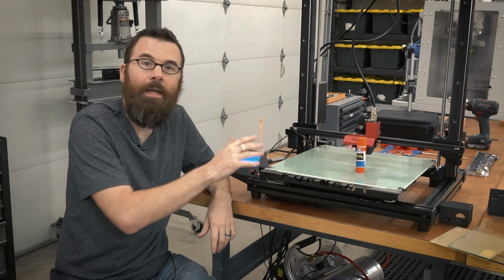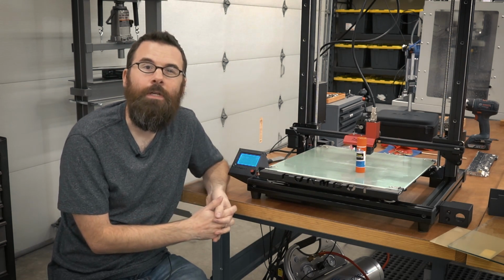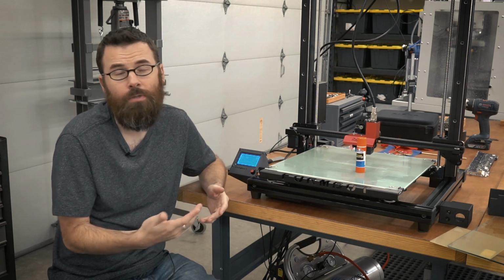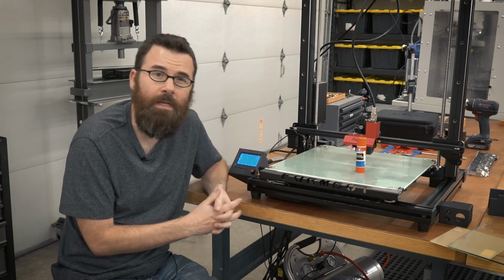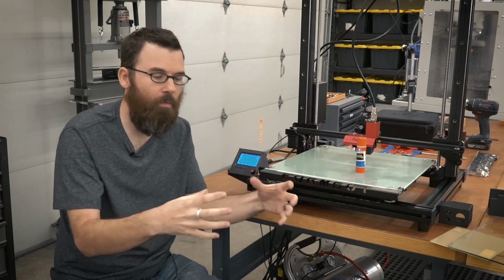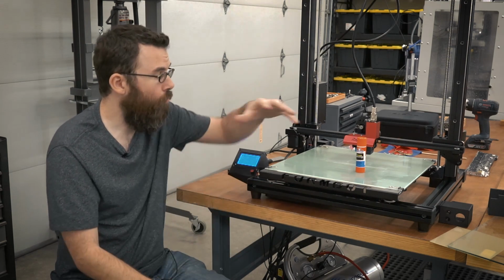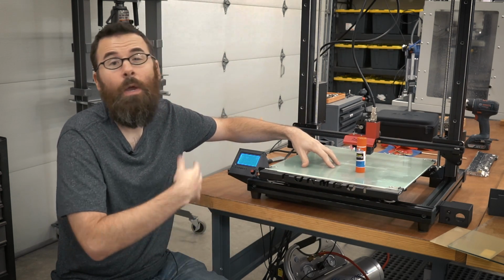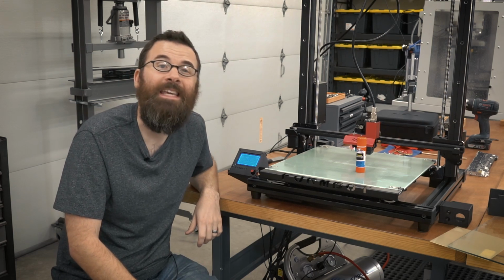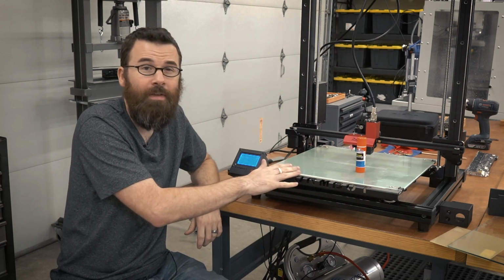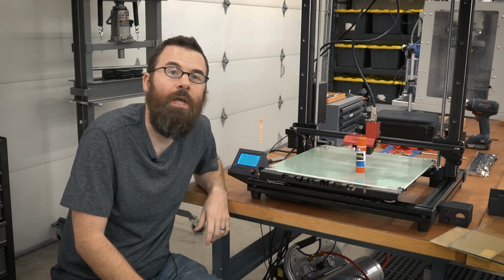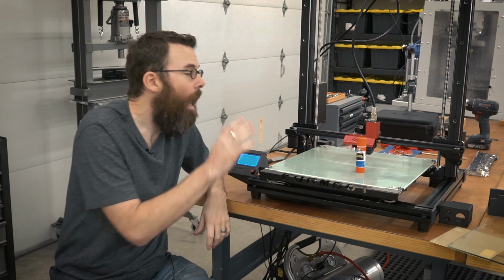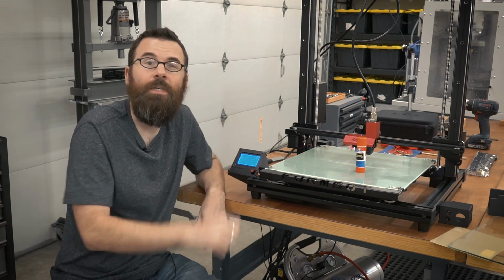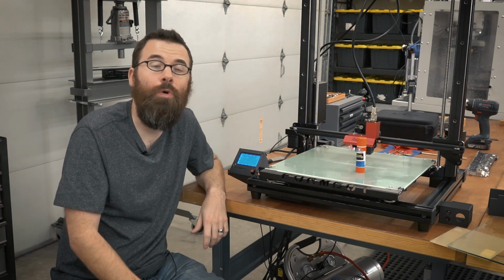Also, heated beds. I am running my bed at 70 degrees. I've tried 60, I've also tried 50. I found that 70 gives the best layer adhesion for that first layer. It really likes to stick to the bed, and when it cools down, I can pop it off really easy. So if you don't have a heated bed, I don't really know what to tell you. You might have a bad time. I've always used a heated bed, and I've always kept it around 70, and that has always worked out really well for me.